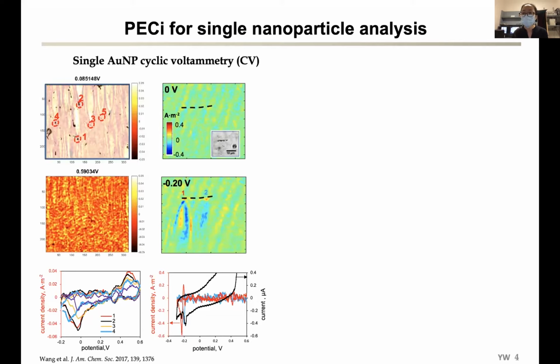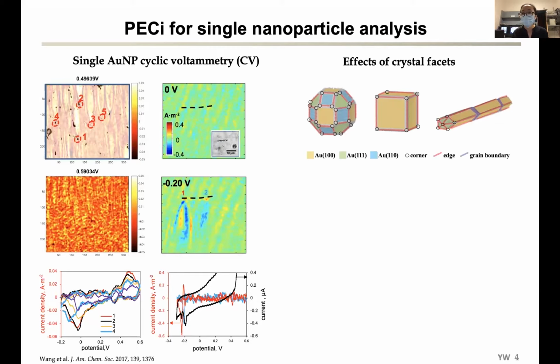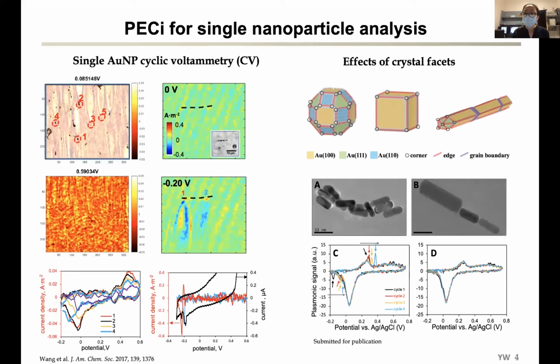Now, a current ongoing project in my lab is we're interested in seeing how the crystal facets of individual particles affect their electrochemical or electrocatalytic activities. And to show you an example, we studied gold nanorods. If you look at the CVs extracted from those single gold nanorods, you can see that there are some tiny minor peaks, which can be contributed by the surface facets like 100 or 110.